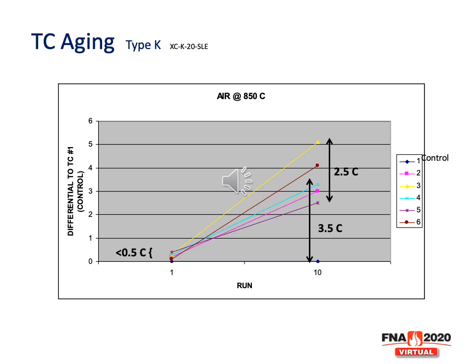Now this happened in air. Later, we ran some more studies of doing the type K TCs down at about 225 degrees C. We saw very little change at that temperature. And then we also ran them in hydrogen up at 850 degrees C, and we didn't see very much change at all in hydrogen. So this really had to be an oxidation of those thermocouple joints.